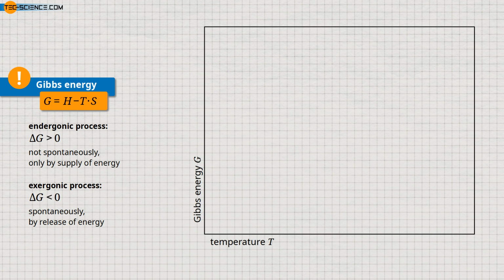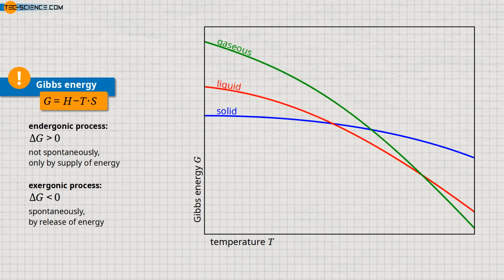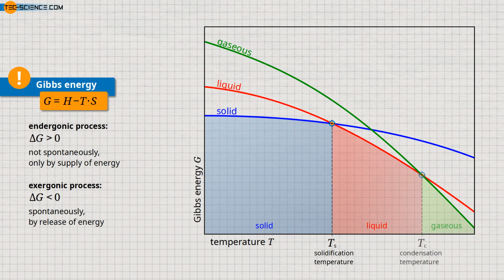The diagram shows the schematic course of the Gibbs energy as a function of temperature for the solid, liquid, and gaseous state of a substance. It can be seen that below a certain temperature, the Gibbs energy of the solid state is energetically more favorable than that of the liquid state. The intersection of the two Gibbs curves indicates the solidification point or, in the opposite case, the melting point of the substance. At the solidification point, the Gibbs energy of the liquid and solid states is obviously the same. Likewise, the vaporization or condensation temperature can be defined as the intersection of the Gibbs curves between the liquid and gaseous states. In principle, only the state of matter with the lowest Gibbs energy is in stable thermodynamic equilibrium.